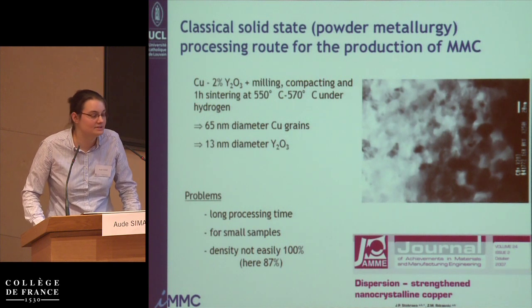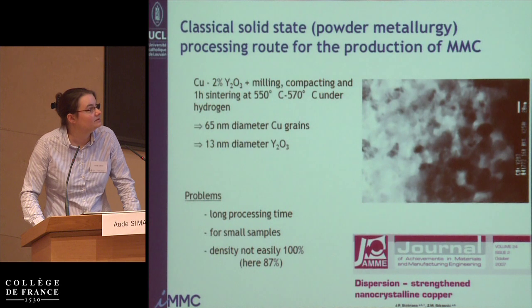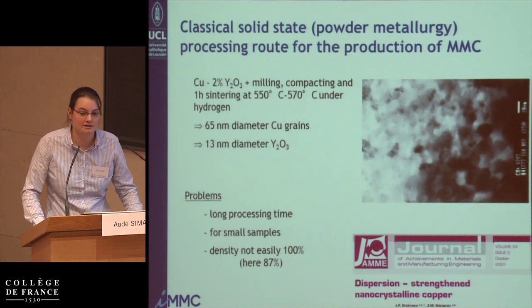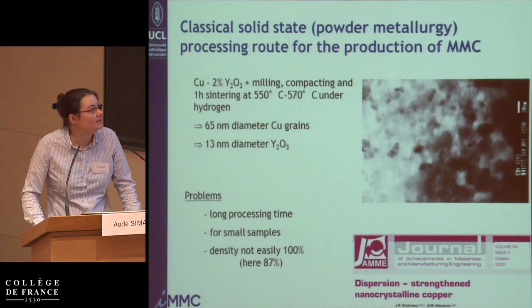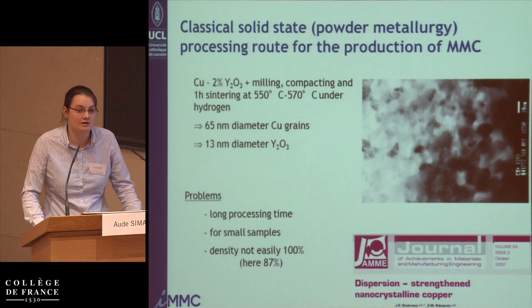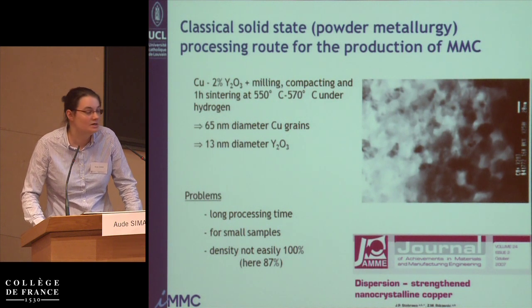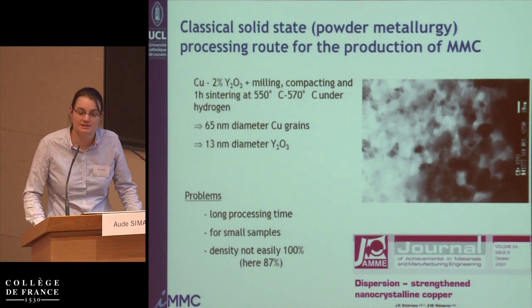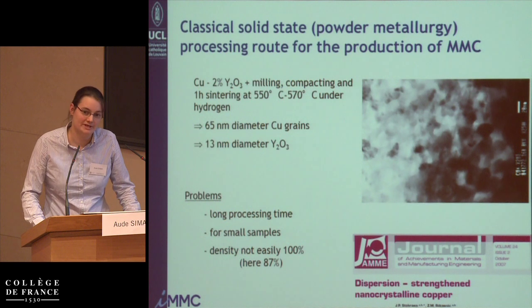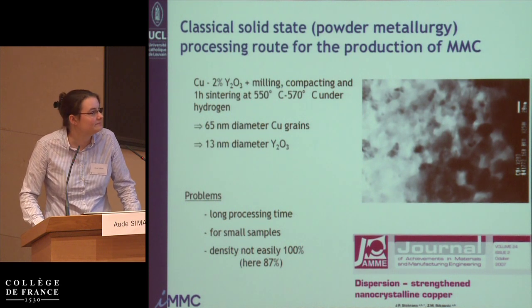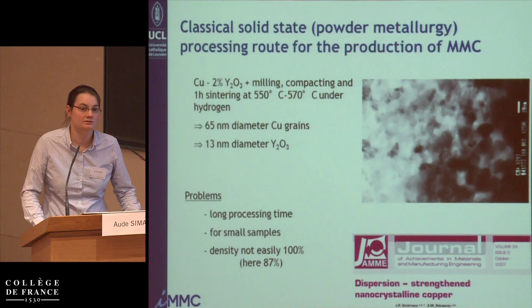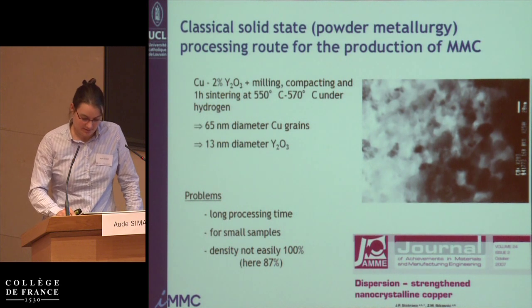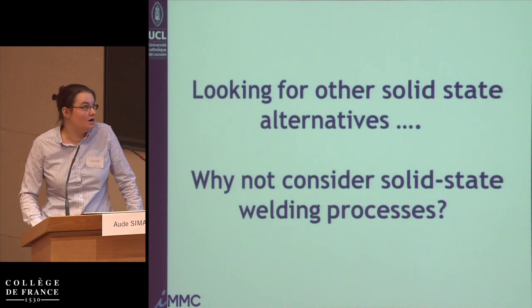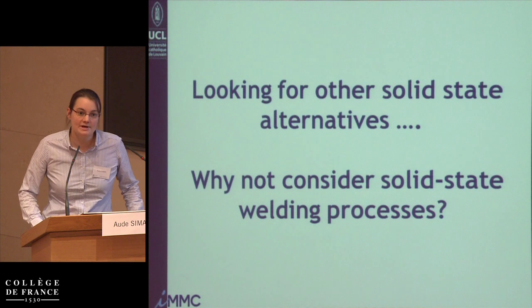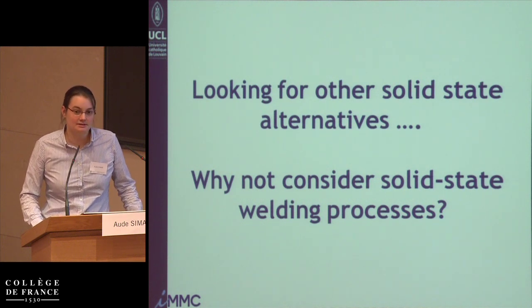Here, the authors of this paper did it with classical sintering, just putting the material in the oven, and so they end up with a material that has a very low density, only 87%. So basically, you have lots of voids in this material, and for the mechanical properties, that's not very desirable. And also you need a long processing time to make such materials, and usually you work with very small samples.